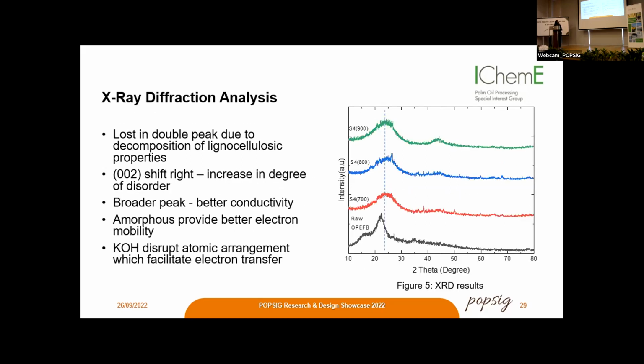Next is the X-ray diffraction analysis. We will focus on the front part of this graph. So when you compare raw OPEFB and the carbonized sample, the loss in double peak here will be due to the decomposition of lignocellulosic properties. When we compare the 002 peak here, an increase in temperature would cause a shift to the right, which means that there is an increase in degree of disorder. However, after 800 degrees, at 900 degrees, the peak shifted back to the left, which means that there is a decrease in degree of disorder, which may be due to over decomposition.